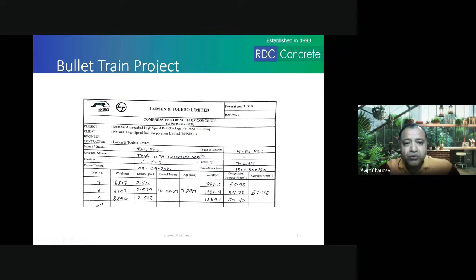And they also were kind enough to allow us to reproduce this sheet of theirs. At 7 days for M50, they have got very close to the target strength, 57.36. And this is what, from their register, we have been able to get at different days. So at 14 days they've got 57, again almost the same. 21 days 66, and 28 days 68 for an M50 grade of concrete. Now mind you, this strength was in addition to a higher workability as compared to their current mix.